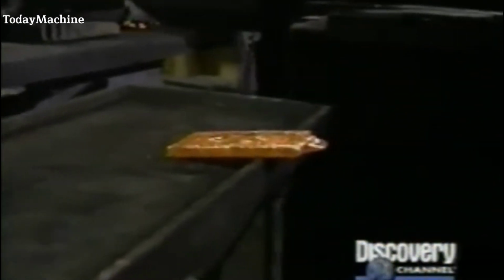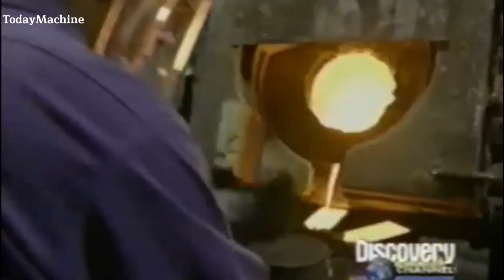To achieve this, the gold is cast into small bars and subjected to electrolysis, a refining method employed by only a handful of mints worldwide. The gold bars are submerged in an acidic bath alongside titanium plates, and an electric current is passed through the solution. Over 2 days, gold particles migrate and coat the titanium plates, leaving behind impurities that sink to the bottom. The result is gold with an astonishing purity level of 99.99%.